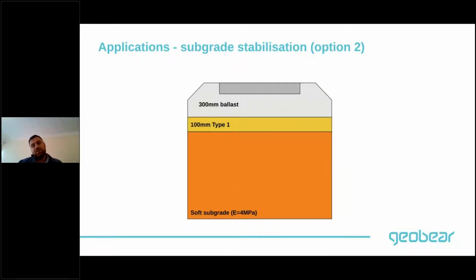The other way of using this is, for example, to use this approach as a maintenance methodology. For example, let's say you've got a railway track already built on a soft subgrade, and it has this kind of typical design: 300 mil ballast plus 100 mil of type 1 or sand blanket. Now we know that this is not really the ideal design for this kind of subgrade, but your track components are still new; they're not old. So your sleepers are not very old. The rails are still okay. And your ballast is still okay, but you've got a soft subgrade, and as a result of that, you're losing your track geometry. Well, what you can do, instead of waiting for the renewal and keep tamping until you get to the renewal, you can use the geopolymer stabilization method to start strengthening the subgrade and reducing that level of deterioration, hence reducing your maintenance.